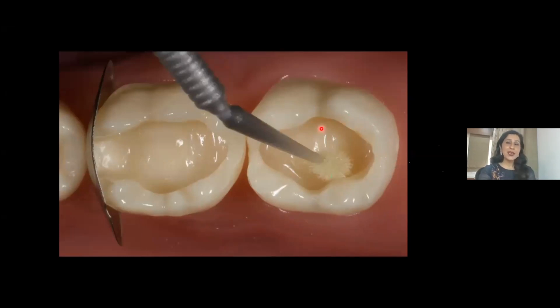20 seconds, it has to be left undisturbed. The amount that has been taken now is a copious amount; the tooth should have a glistening effect. All the line angles, point angles, the floor, the walls, the cavosurface margin should all be glistening. That means that you have a substantial amount of bonding agent. Now wait for 20 seconds because it has to do all those things which I told you. And now after waiting for 20 seconds, you will take a gentle stream of air and remove the bonding agent.